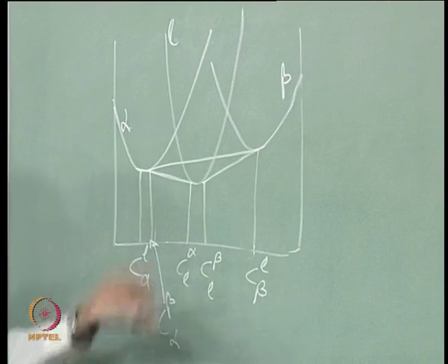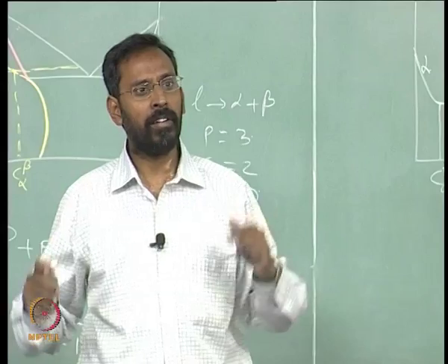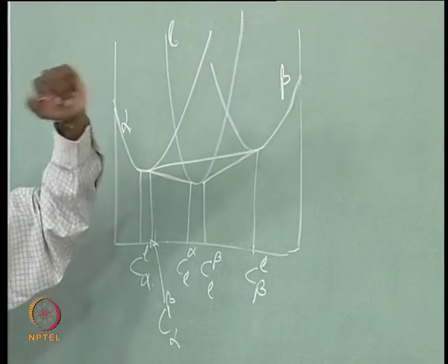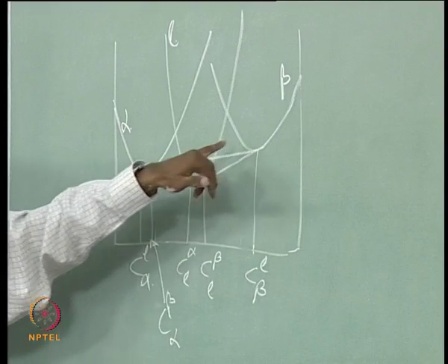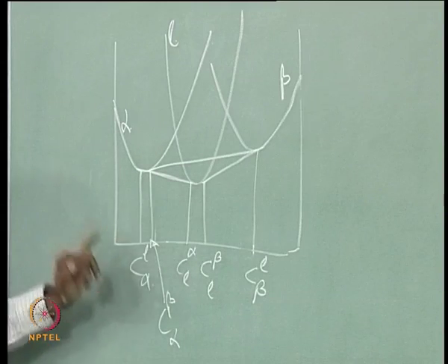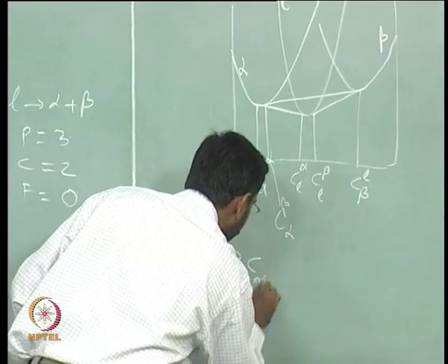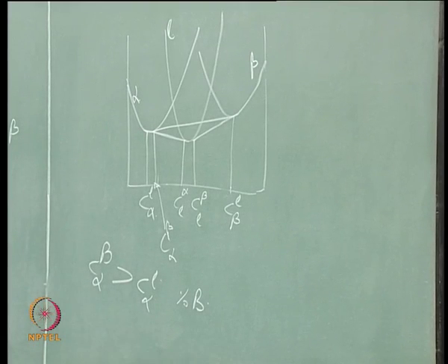Why? Because the beta curve is at a higher level than the liquid curve, liquid is at a lower level than the beta. Why? Because at that temperature liquid is more stable. Because liquid is more stable, the liquid curve has to be lower than the beta curve, and because one curve is lower and another is higher, when I am drawing common tangents, it is not possible for the common tangent between beta and alpha to have a composition to the left of the alpha and liquid, it has to be always to the right of the alpha liquid. So, that means C alpha beta is higher than C alpha liquid in terms of percentage B. It has to be that way,